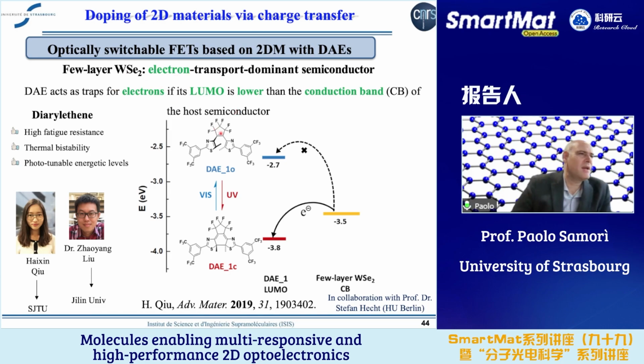And on top of the tungsten selenide we put a 3 to 5 nanometer thick spin-coated layer of diarylethene. And diarylethene, as I mentioned before, has energy states that are different in the open and the closed state. Given the conduction band of the tungsten diselenide, we have designed and synthesized, in collaboration with Professor Stefan Hecht in Berlin, a diarylethene whose LUMO level in the closed state is in the band gap of the tungsten selenide, and in the open state is out of the band gap. And therefore, we can switch the diarylethene from one state to the other.